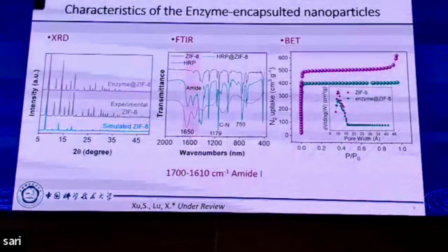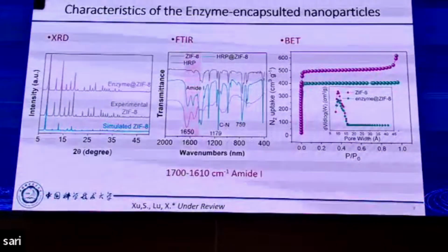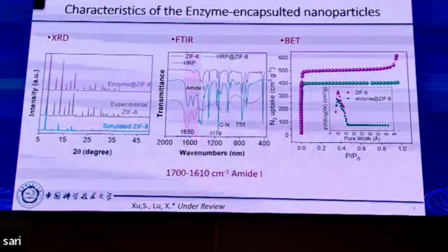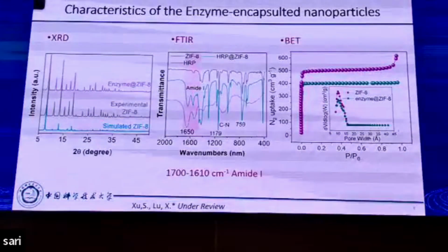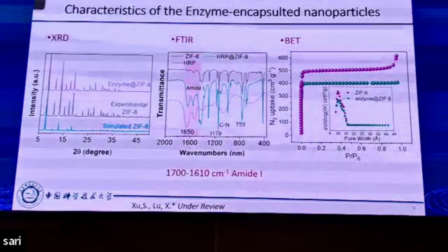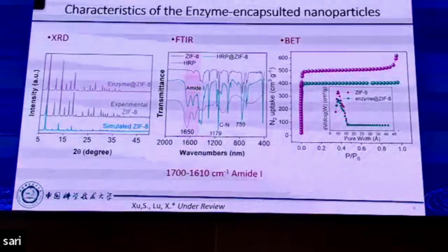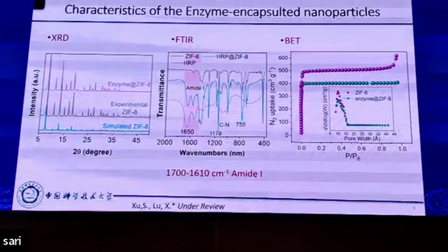In FTIR, we use it as evidence to confirm that this enzyme is encapsulated within the nanoparticles. Regarding the BET, it shows that after the encapsulation, the pore size of this ZIF nanomaterial does not change a lot. So all of them show good evidence of these enzyme-encapsulated nanoparticles.